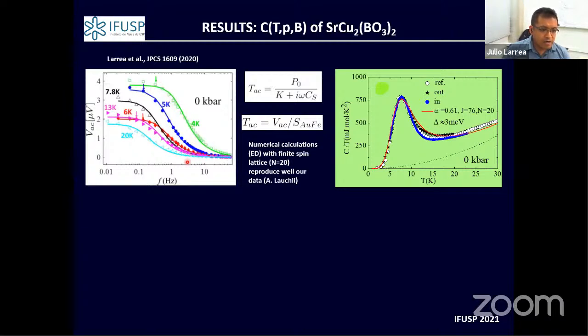But overall, this curve of the specific heat, for instance, is obtained by fitting the frequency scan of the modulated signal. Then for each curve you obtain a point of the specific heat, plotted against the temperature. So this measurement, for instance, takes around 3 weeks just to determine precisely the specific heat of the sample.